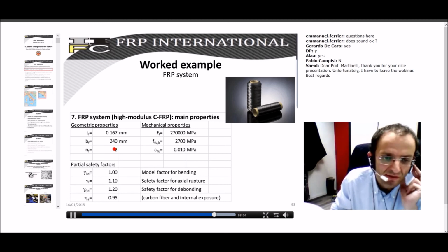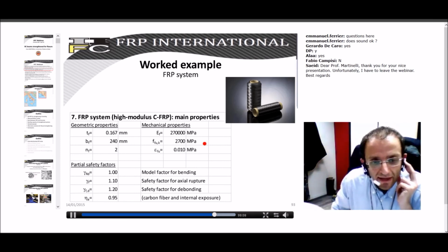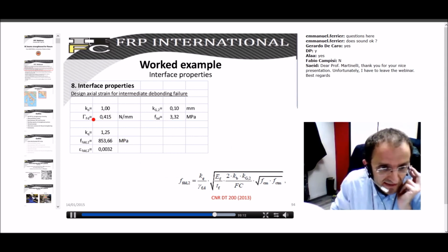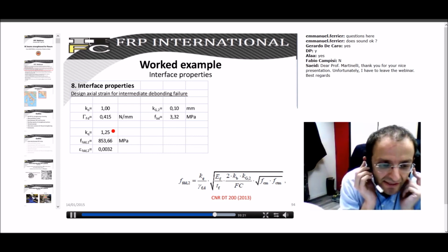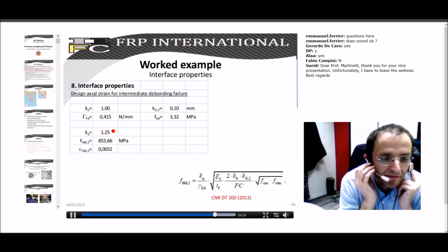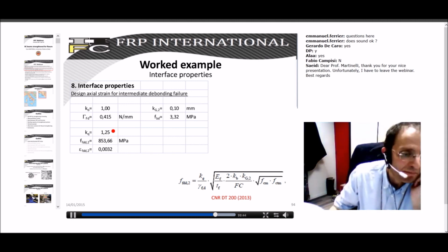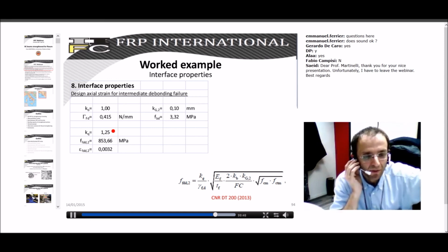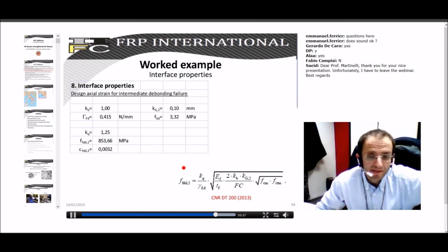These are the properties. We consider to install just two layers, two plies of FRP. We consider these parameters, which are related to some safety factors, which are provided by our regulation. And then, according to our calculation, we can calculate the design value of the interface fracture energy and the corresponding effective axial strain resulting in intermediate debonding. So as you see here, this is 3 per mil, 0.3%, which is 5 times lower than the ultimate strain resulting in the rupture of FRP. So actually, due to the intermediate debonding, we have to reduce significantly the effectiveness of this external strengthening. So we have to work with this.